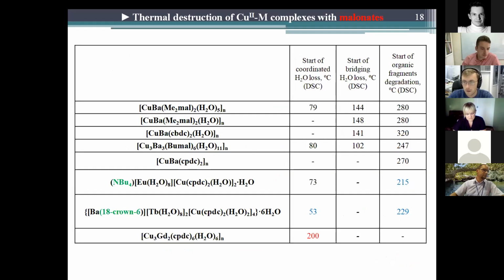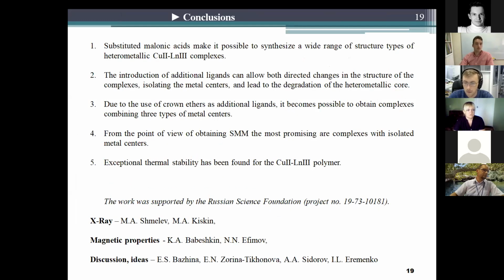Most of the cyclopropane dicarboxylate complexes have low stability compared with substituted malonate analogs, but the synthesized copper-gadolinium cyclopropane dicarboxylate demonstrates the highest thermal stability, over 200 degrees. The possible reason is encapsulation of water molecules in the polymeric structure and stabilization of them by hydrogen bonds. So we can conclude that substituted malonic acids make it possible to synthesize a wide range of structure types